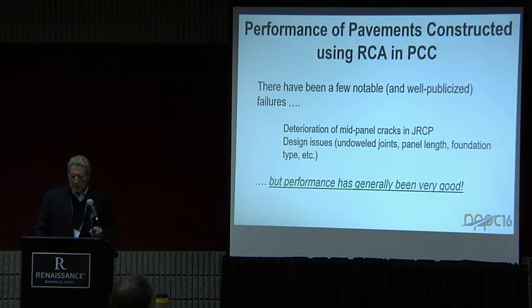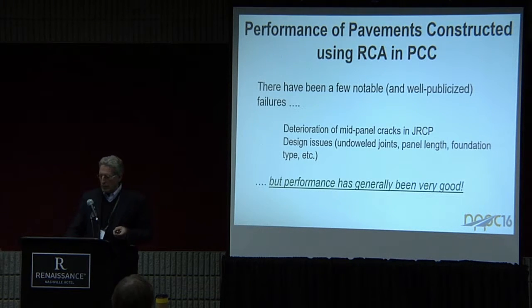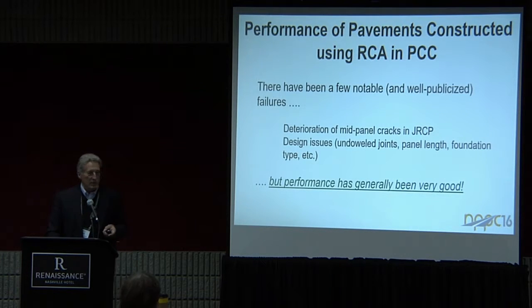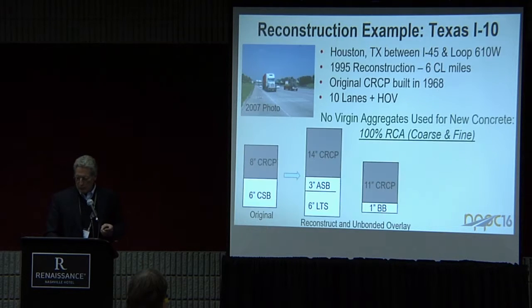Okay, performance of pavements constructed using crushed concrete. They've generally been pretty good. There have been a few notable failures, pretty well publicized failures. Saw Andy Bennett here. Michigan had some of those back in the 80s, and there have been a few others. Kind of tracked down what was going on. We were learning at the time, learning about the panel lengths and panel spacing and a lot of other things. There were some design issues on some of those projects. But I think the general consensus today is that you can use crushed concrete in new concrete mixtures as long as you pay attention to the details and what we've learned from those failures back in the 80s. We should expect good performance now.